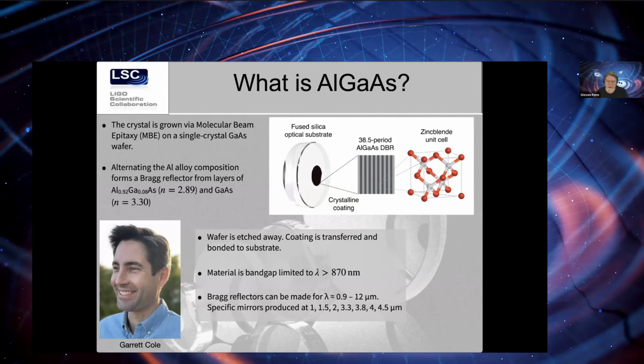This was a difficult technology that took us a lot of years to work out the kinks and lowering the noise that was involved in that transfer and bonding process. But now that is done, we're getting very good results overall. And this allows this coating to be used on a wide variety of substrates and anything that is above the band gap up to about 4.5 microns.